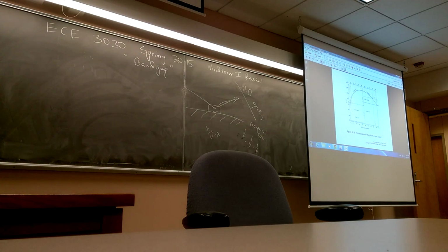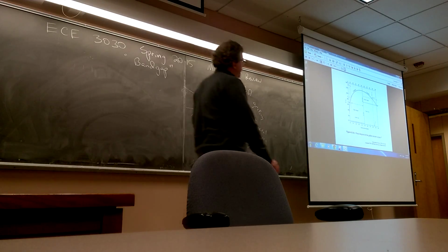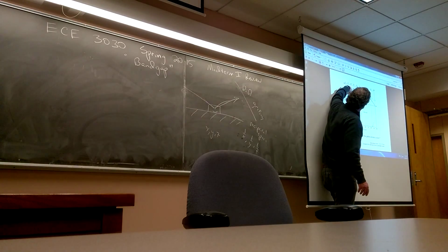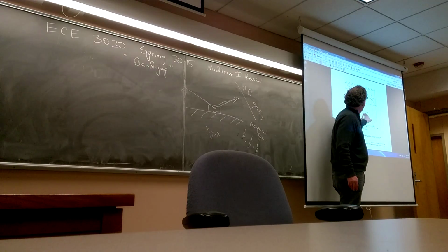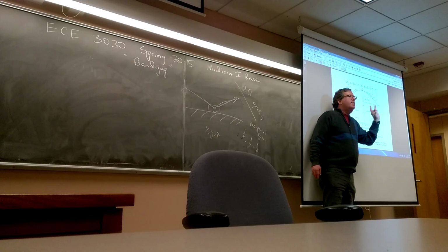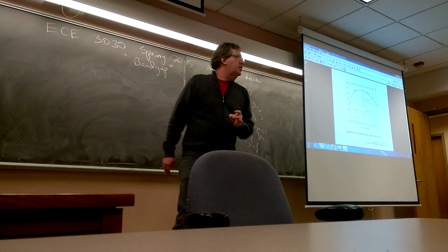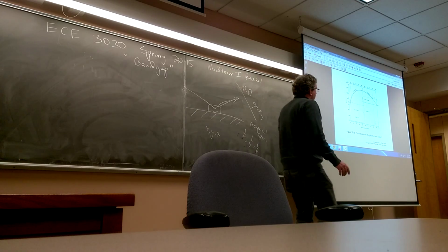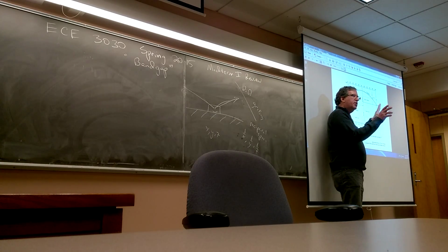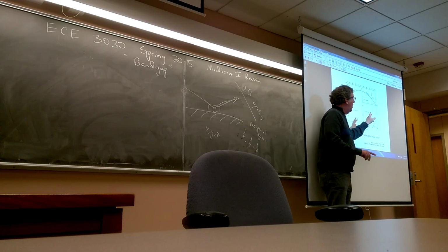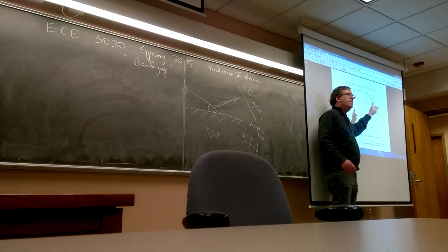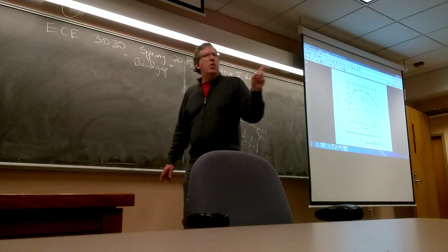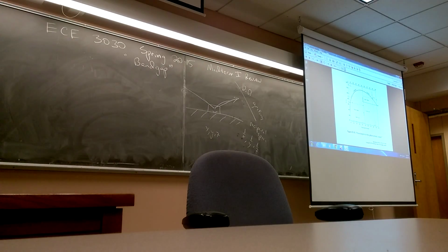So this is the phase diagram, which is a little bit beyond this, but you heat it up to liquid, above the liquidus, cool it down, and it actually comes over to this tie line, and it condenses out as stoichiometric gallium arsenide. It was a huge discovery in the early 70s when they could realize that they didn't have to get the gallium and the arsenic ratio exactly 1-to-1 to 9 significant digits. Mother Nature, through the phase diagram, only allows it to condense in 1-to-1 ratio. So Mother Nature gave us a good one there.